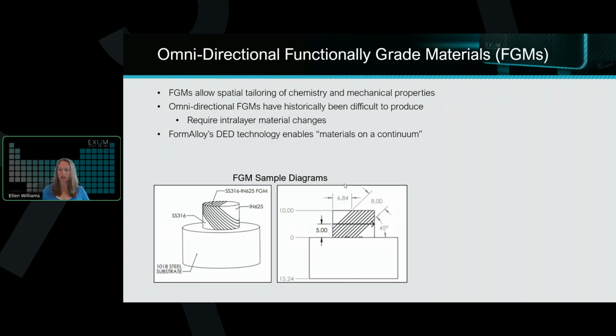So what you're looking at on the bottom here is a diagram of one of these omnidirectional functionally graded materials, where you see we've got a steel substrate and then the printed stainless steel 316L transitioning to Inconel 625 at a 45-degree angle over an 8mm range. So, pretty impactful that they're able to create their technology that allows them to do that material change, as well as some innovative powder feeding mechanisms that allow this to occur.